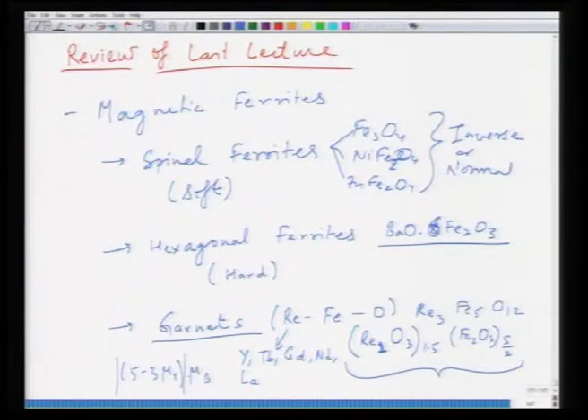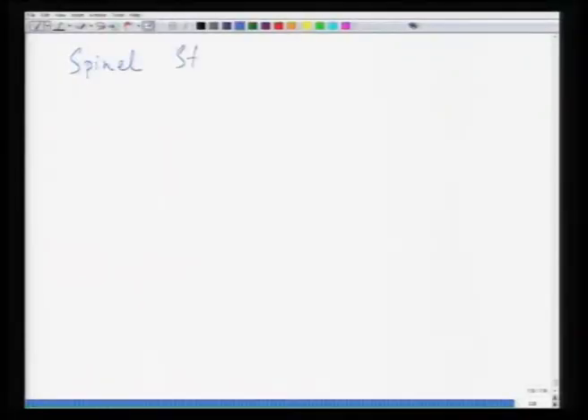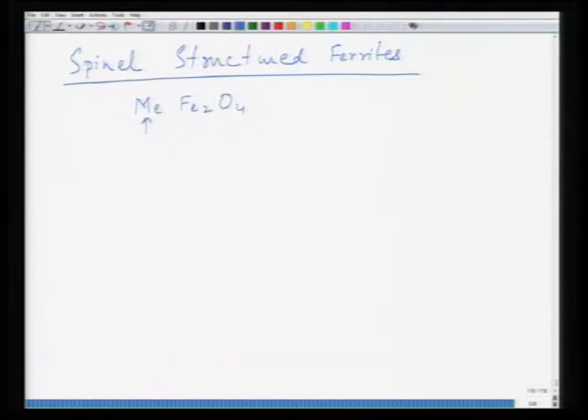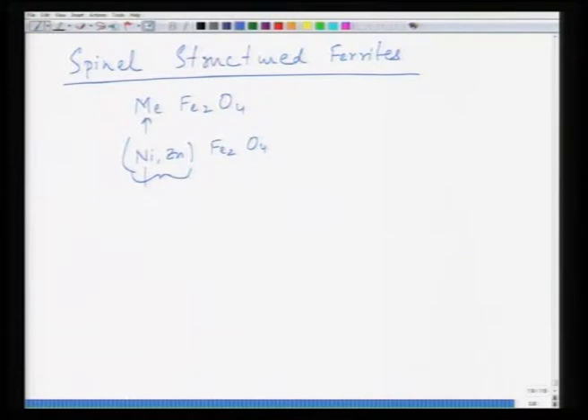This is essentially a summary of what we discussed last time. What we will now take up is one more thing that was not discussed last time, especially in the case of spinel ferrites. In the case of spinel-structured ferrites, consider the formula MeFe₂O₄ where M is some metal ion. This metal ion can be a mixture such as Ni₁₋ₓZnₓFe₂O₄. Here nickel is a magnetic ion, but zinc is not a magnetic ion — it has zero magnetic moment — but by careful mixing of these two you can achieve a magnetic moment which is actually higher than the parent compound.